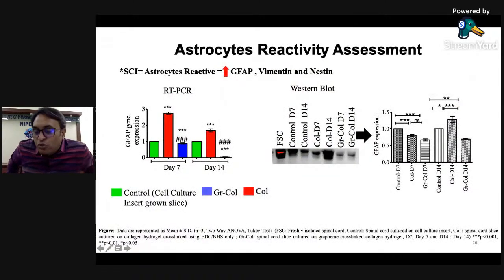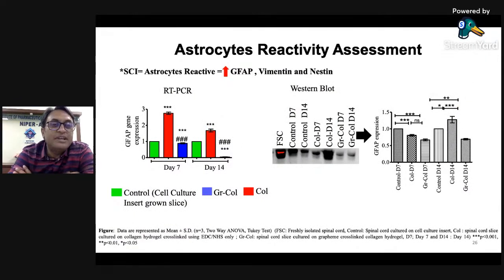Hence, we first looked into the reactivity of the astrocytes, and in this RT-PCR data, you will find that GFAP, which is a marker for reactive astrocytes, has very high expression in collagen alone. But with graphene incorporated, at day 7 it is equal to cell culture, and by day 14 it further suppresses the reactivity. This means it is controlling the reactive nature of the astrocytes, because reactive astrocytes are not good - they lead to scar formation.